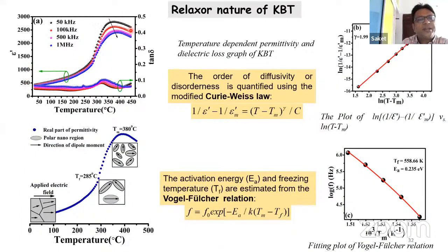See, this is the typical dielectric plot for KBT, because you have seen the slanted loop. Another thing is that with frequency, this temperature shifts. I told you that a relaxor will show this, and the same in the tan delta also. Even here, in these graphs, I can tell you it is nothing great. You know the Curie-Weiss law now, 1/ε = (T − Tm) or sometimes (T − Tc) or theta, divided by C. So here we have used gamma.